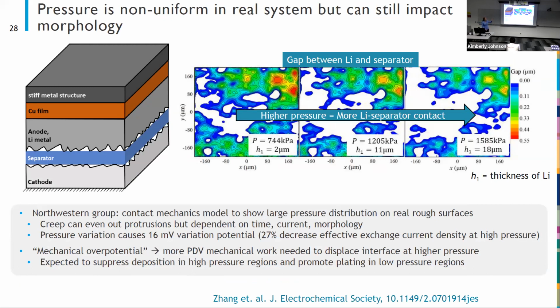So what we're looking at here is the gap between the lithium and the separator. And white means that there's no gap, we're in contact. And if it's colored, and more so red, we're looking at a larger gap where there's space between the separator and the lithium. So they included a lot of things in this model, including creep and mechanics. And we looked at the effects of lithium growing and causing an increase in pressure because of the volume change.